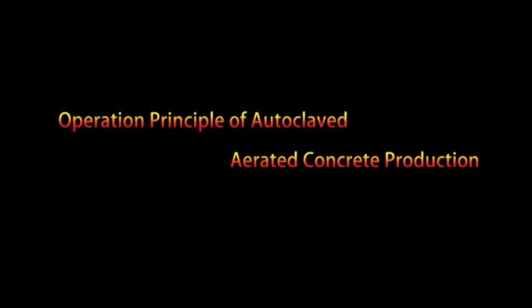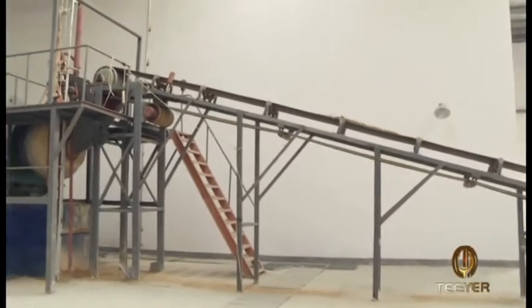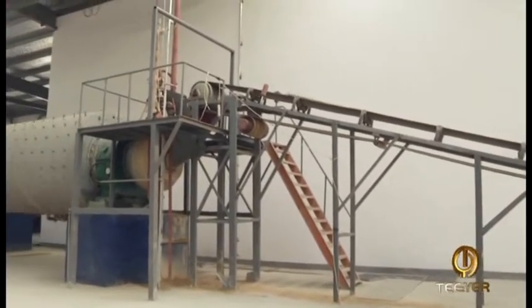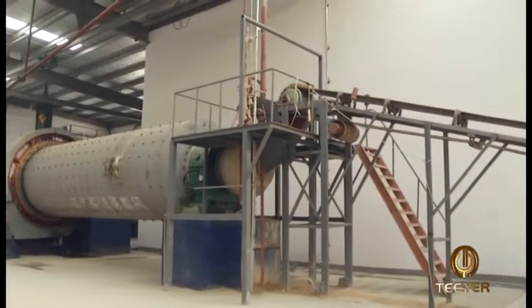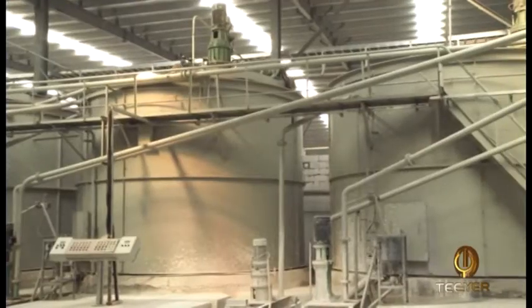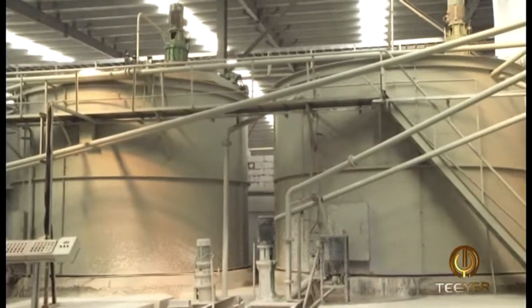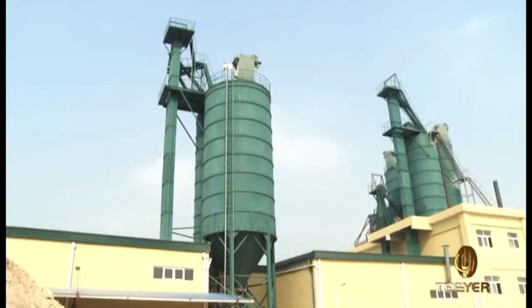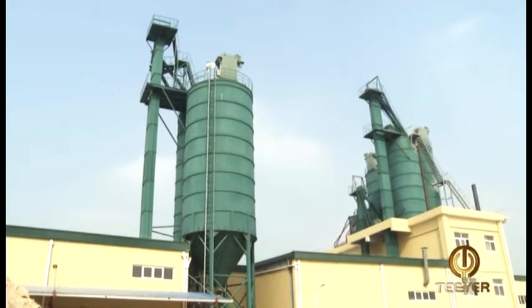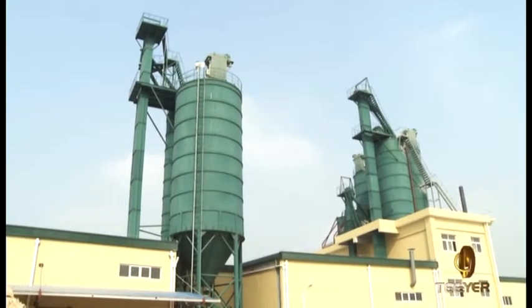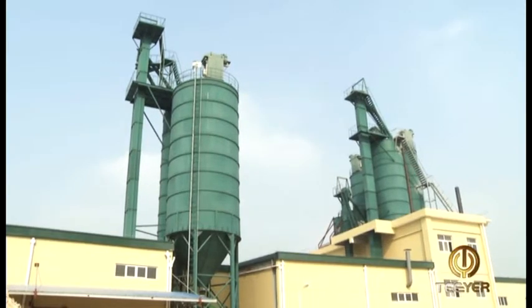Operation principle of autoclaved aerated concrete production. At first, pulverized fly ash or sand are ground through the ball mill and made into slurry stored in the storage tank. The cement and the lime which have been processed are respectively conveyed to the cement silo and lime silo.